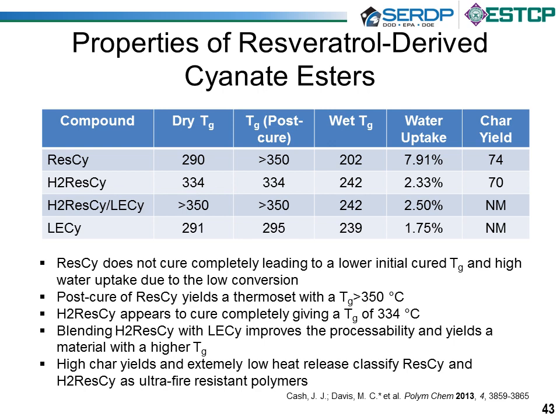The hydrogenated version also gives a remarkable glass transition temperature of around 335 degrees Celsius, and it does cure completely. It has a moderate water uptake of 2.33%. We can blend it with LECy, which is another bisphenol. This is a petroleum-based bisphenol that's a liquid. It's much easier to process. The co-resin, when cured, has a glass transition temperature greater than 350 degrees C, again, quite remarkable, and moderate water uptake.